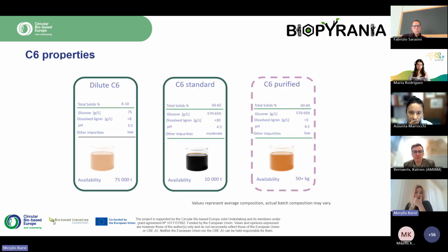So let's take a closer look at the properties of our streams. For the C6 stream, the initial solution that comes out of our system is relatively dilute. After the evaporation step, the total solids increase up to 60 to 65%. The dissolved lignin content is below 30 grams per liter, while other impurities such as HMF, furfural, organic acids are present at moderate concentrations. Following the adsorption purification step, the lignin content is reduced to below 5 grams per liter, and the levels of other impurities are significantly decreased.